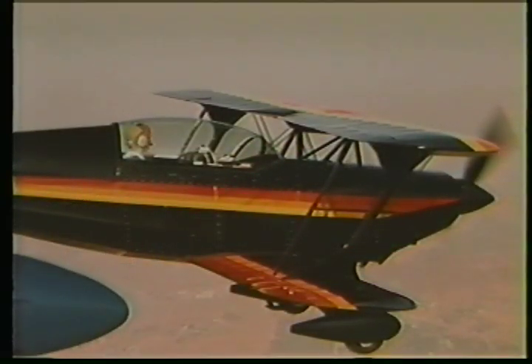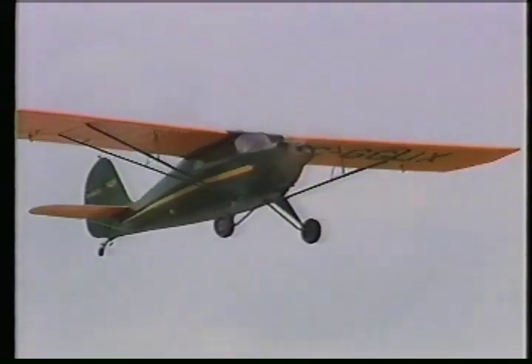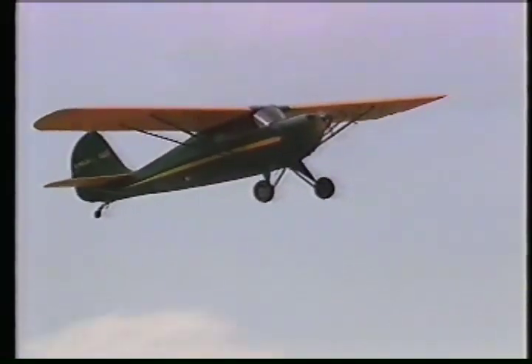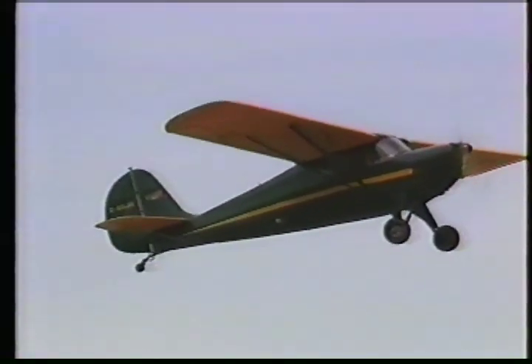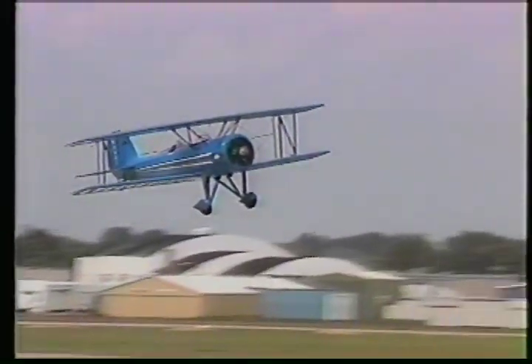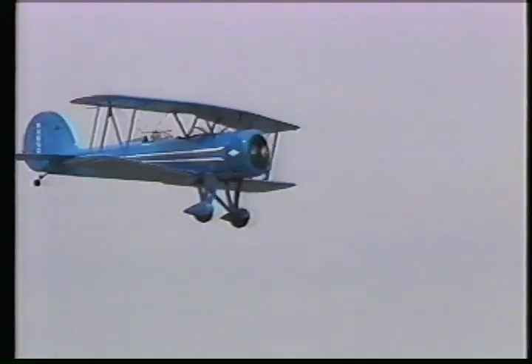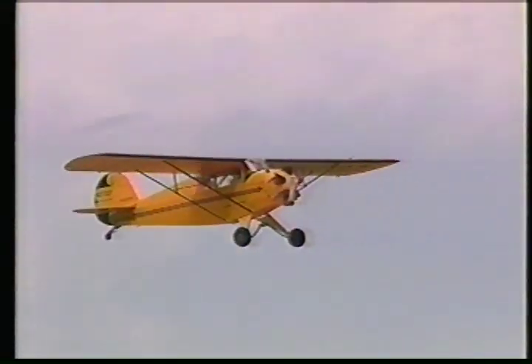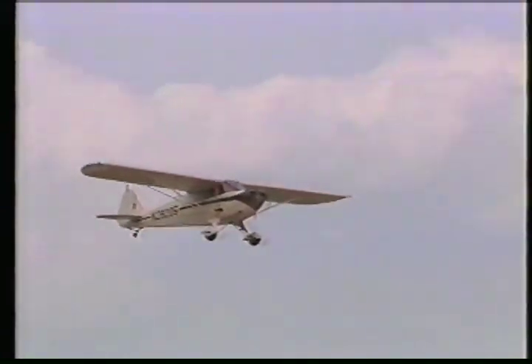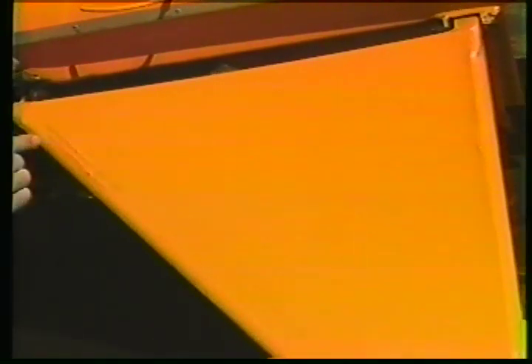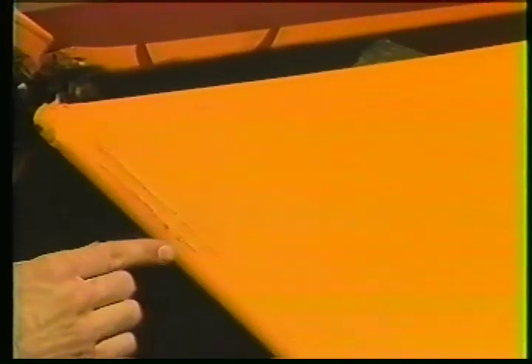The effect from fabric ballooning between the ribs is a change in the airfoil thickness and shape, which may change the center of pressure travel and safe CG range. Most noticeable when comparing to the original flight test data is a loss of airfoil efficiency, which increases the takeoff run and reduces the rate of climb, service ceiling, and speed, and may change the stall and flight characteristics such as spin recovery. A loss in performance is usually blamed on the engine or propeller. Loose fabric rippling in the prop wash area will eventually fatigue and crack any finish, and the cracks are always blamed on the coatings rather than the workmanship.